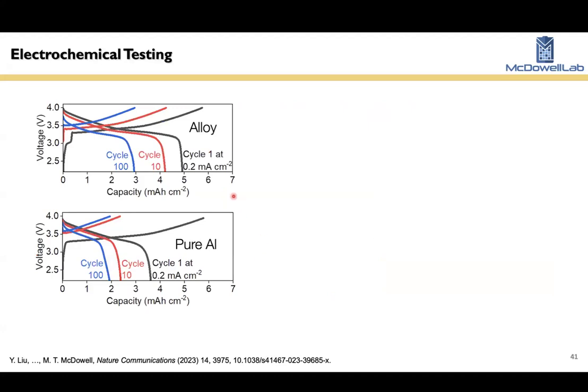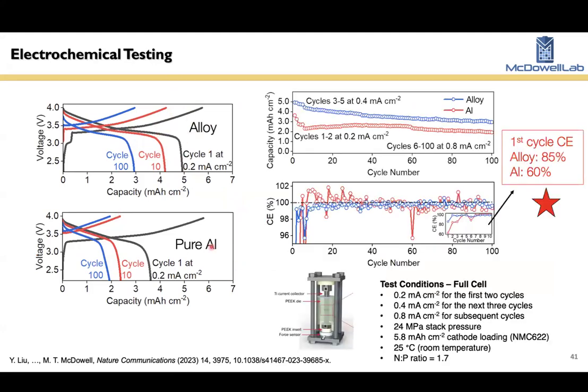And when you test these in solid-state battery cells, you see that this aluminum indium alloy has much higher capacity and better cyclability than just the pure aluminum. And one of the most important things, it has a much higher initial coulomb efficiency as well. So the indium phase within this aluminum microstructure reacts with lithium, just like aluminum does. And it has very high transport characteristics, high diffusivity. And so instead of trapping lithium like pure aluminum, the interspersed lithium indium phase allows for lithium to be removed from the structure more effectively and increases the initial coulomb efficiency.